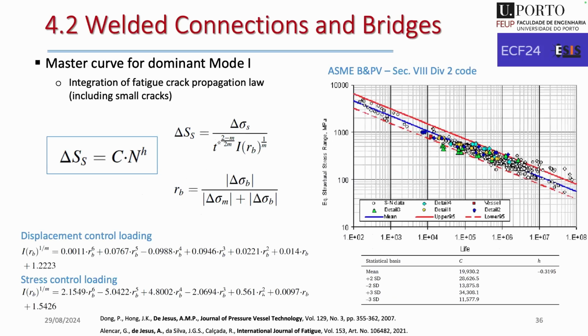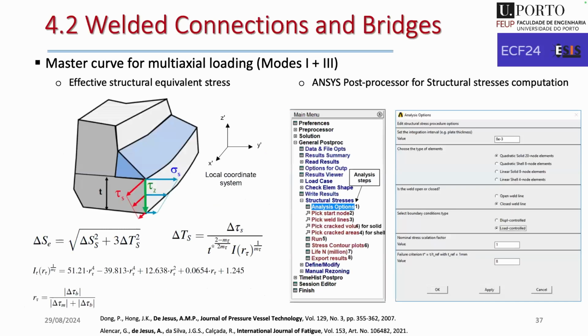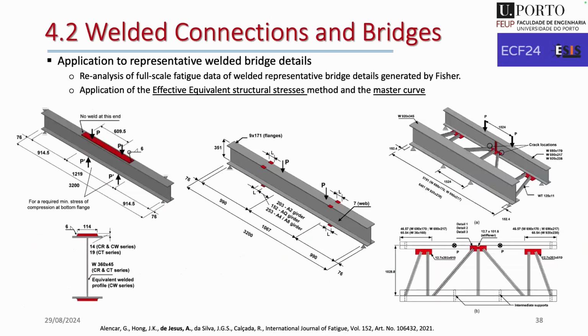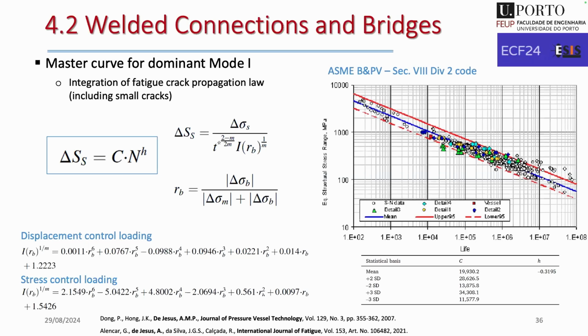Integrating the crack propagation law, accounting for small cracks effect, and accounting for the stress intensity magnification factors for joints, typical on joints, we were able to reach a master S-N curve with a new definition for the structural stress, which accounts for the stress linearization, the loading type, and the size of the plate under analysis. With that, we were able to demonstrate that it worked for pressure vessels components.